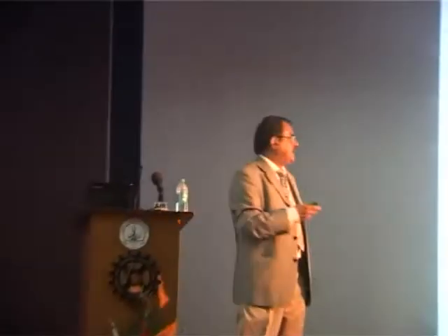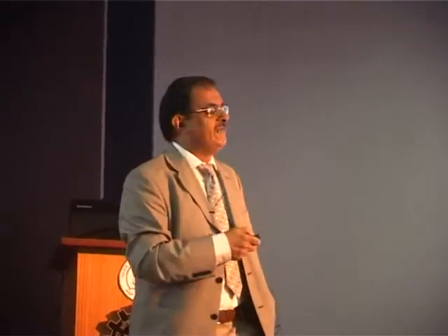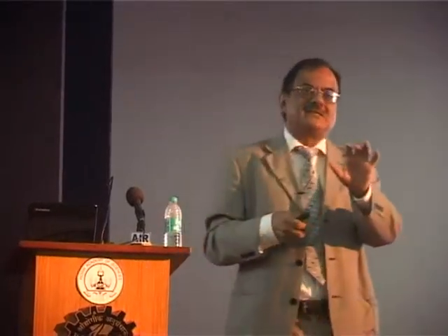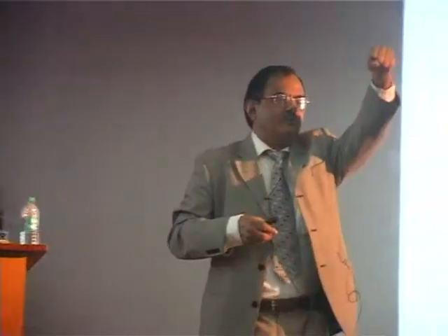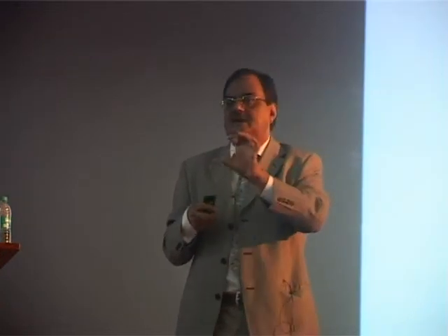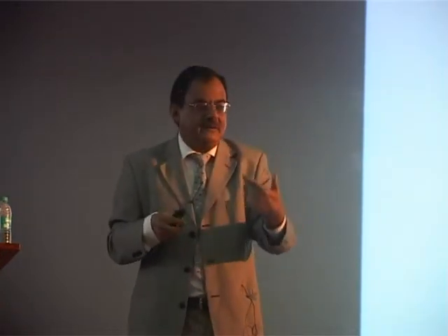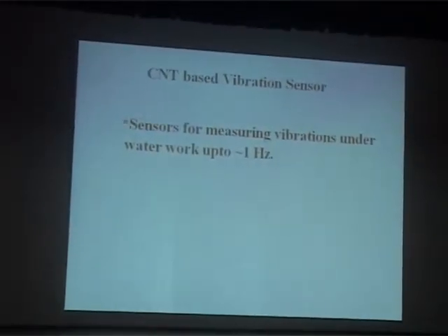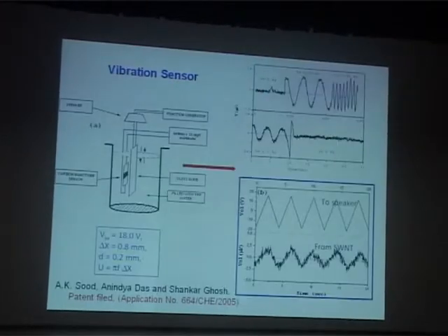Before I discuss that, I just wanted to tell you some very simple applications of this, which might have relevance in the context of Goa: underwater detection of vibrations using nanotubes. The available sensors are pressure sensors. When you put them under the sea, the pressure gives you a voltage because of piezoelectricity. All those sensors are not very useful below 1 Hertz because 1 over f noise is too high, so you cannot detect vibrations below 1 Hertz. But in nanotubes, this is not the case.